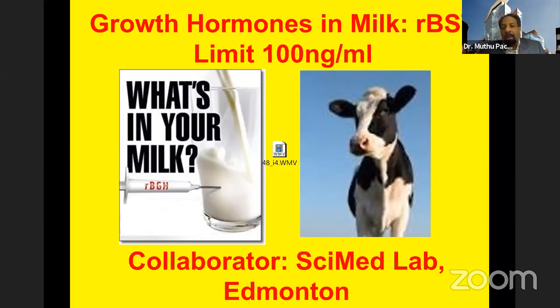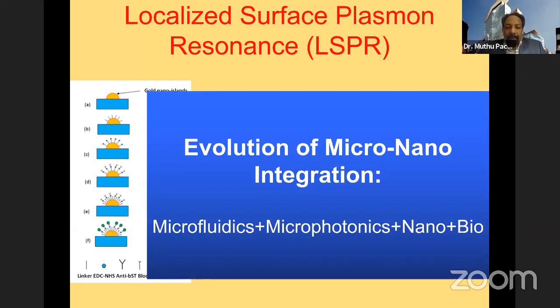Typically, most of the countries do not allow growth hormones in milk. And if at all they allow, the limit is 100 nanogram per ml. The thing is, we do not have handheld devices to basically detect this. So we started working on finding different platforms to find how to detect these growth hormones in milk. One of the things we found out was LSPR, which is localized surface plasmon resonance-based microfluidic systems, was very, very effective for this case.